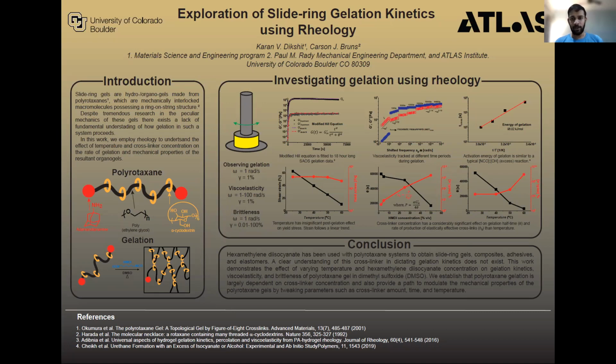So I employ rheology to observe gelation by doing a time sweep. I track viscoelasticity at specific frequencies and strains across the gelation temperature or gelation time. And finally, for the post-gelation mechanics, I do a brittleness test.